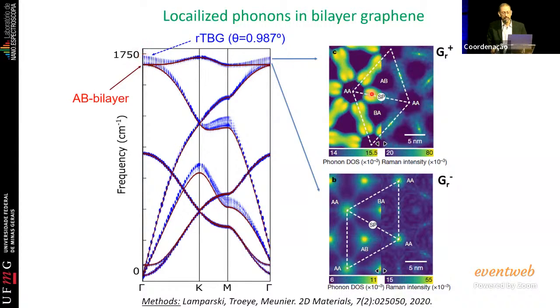And what these fellows show theoretically is that if you look at the phonons at high frequency here, they are localized at the strain solitons, at the domain walls. And if you look at the phonons at low frequency, they are localized at the AA sites.